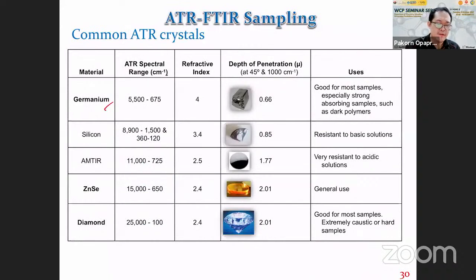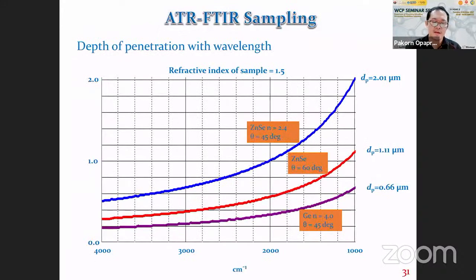And these are some examples of crystals that are employed to make ATR accessories. Each one of them has a different refractive index. Therefore, each one will provide us a different depth of penetration into the sample. If we use the same type of crystal but a different angle, you can see zinc selenide here at 45 degrees, the depth of penetration is higher than at 60 degrees. These two lines come from the same crystal. So we go deeper, around 2 microns for zinc selenide at 45 degrees, and only 1.1 microns at 60 degrees.